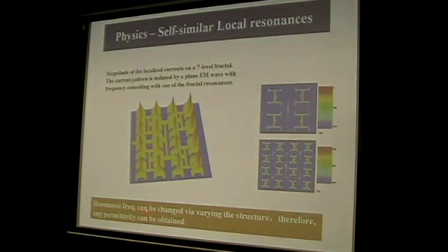So the resonance frequency can be changed by changing the structure. If you want to have a lower frequency, you just scale the system to a larger scale. If you want to have a shorter wavelength, you just scale the whole system down by a factor. So that means we can design the structure to have any permittivity that we want, basically.